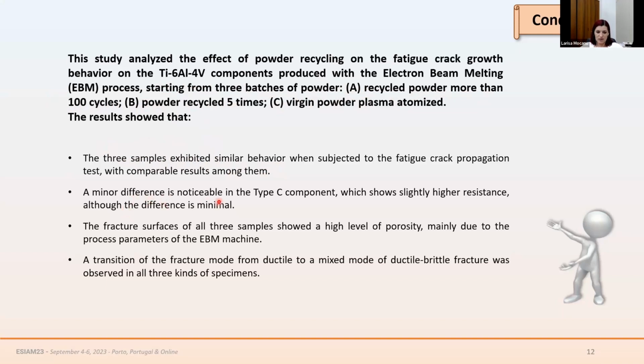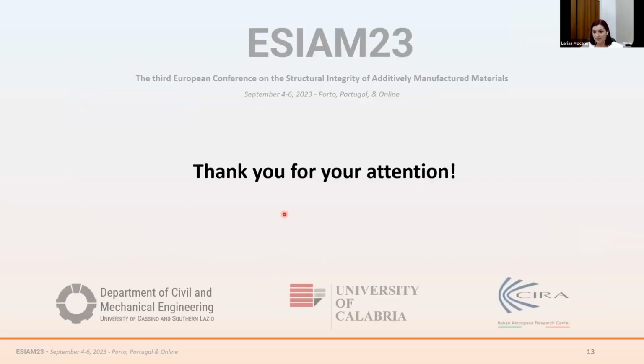A slight difference was observed in the type C component, which is the virgin one, although this difference was minimal. Regarding the fracture surfaces, we observed a high level of porosity. This porosity and the defects are mainly due to the process parameters of the electron beam melting machine, so they are not related to the recycling processes. And also, we observed the transition of the fracture mode from ductile to a mixed ductile-brittle mode in all the three kinds of specimen. And also in this case, as I said, there was no relevant difference regarding the recycling processes. So thank you for your attention.